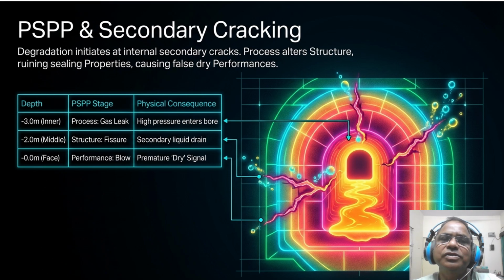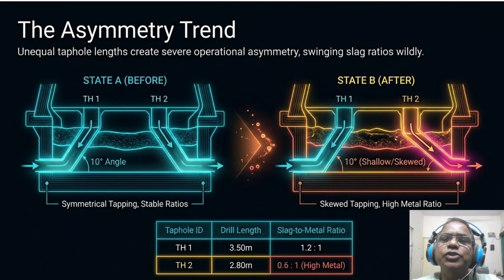So this is the so what of taphole forensics. These internal cracks cause false dry performances where the operator thinks the furnace is empty but the hearth is actually still half filled. So you end up plugging the hole early, leaving liquid behind and setting the stage for a hard chill. We must eliminate this secondary crack if we want to trust our dry signals again. So when these cracks and wear rates are not uniform across all tapholes, we develop a dangerous asymmetry in the hearth. And this upcoming slide compares two hearth states.